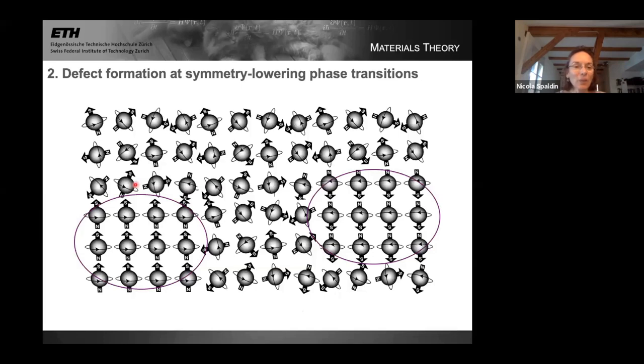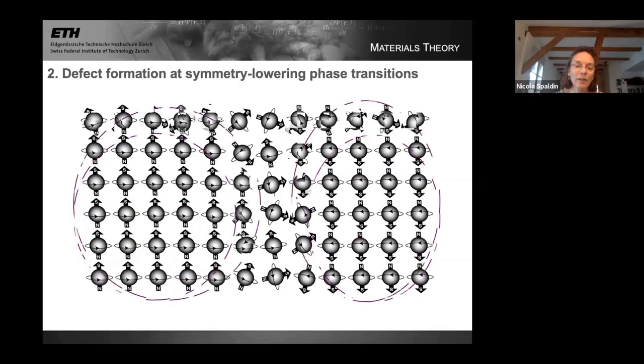Another feature, which is perhaps not quite as obvious or something that we think about as often, is that associated with a symmetry lowering phase transition is the formation of defects. And here I've made a sketch of a paramagnetic material that's approaching the Curie temperature from above. So I'm cooling it down and it's just about to reach being ferromagnetic. And one region of the material is starting to fluctuate into its ferromagnetic state. It's got a correlated ferromagnetic region and maybe it has spin up. And another region far away also is starting to become ferromagnetic, but it could have spin down. And as I cross the Curie temperature, these regions grow into domains.